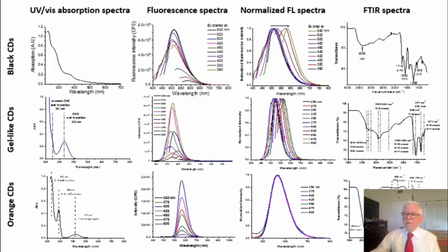For fluorescence measurements, you can see that depending on the wavelength of the excitation, there is a shift of the photoluminescence spectra. And this shift is quite important for the top-down approach or the bottom-up approach. So we have the bottom-up here, and we see this shift when we excite at different wavelengths, from low wavelength to high wavelength of excitation. There is a shift for the luminescence. As you know, for a pure fluorescent molecule there is no shift. With excitation at a different wavelength, the photoluminescence is always at the same wavelength, but not for the carbon dots. The hypothesis we attribute it to is surface state formation, and the second is linked to the possibility of producing fragments that are fluorescent.